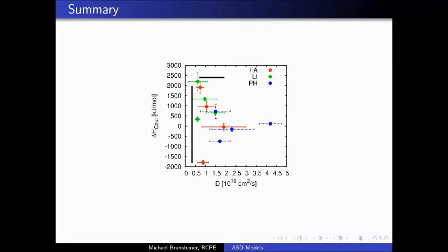Well, for the other compounds where we found that the mobility is rate limiting, we see basically the opposite. We see that we have a relatively small range of energies for the four different polymers, but a comparatively large range of diffusivities. But this is good in a way, because this would enable us maybe in the long run, if you do more such calculations, to define some kind of thresholds that should explain whether the stability of a certain compound is diffusion limited, or energetically limited.